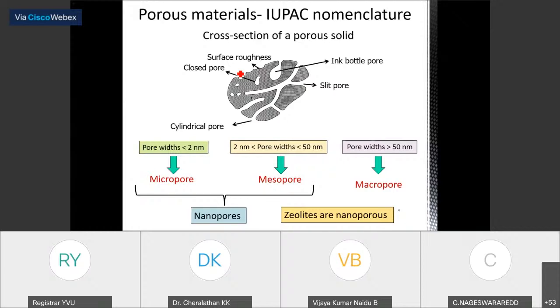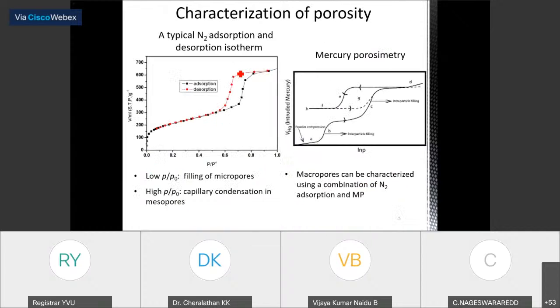And when we talk about this kind of porous materials, how to know whether a material is having micropores or mesopores or macropores? So we need some characterization techniques. Often, nitrogen adsorption and mercury porosimetry are used to characterize this kind of porous materials. For characterizing microporous materials and mesoporous materials, people generally use this nitrogen adsorption technique. So this is a typical nitrogen adsorption isotherm of a material which is having both micropores as well as mesopores.